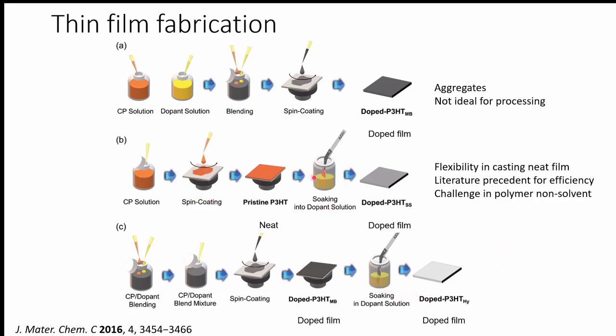So for my polymer, what you're going to see throughout this presentation is that I made a neat film and then I dipped it inside the dopant solutions, and then I got the doped film. And you might ask, why did you do this instead of just mixing them together and putting this on glass? Well, because when you dope them and you have these ionic compounds, they do not like to stay in solution. They start becoming aggregates and they precipitate. So it just becomes a whole hassle to put them on a glass substrate properly without the whole thing turning out to be a mess.